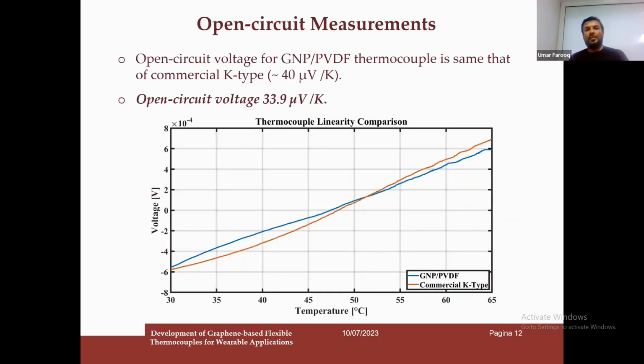So here are the open circuit measurements. They show us that the PVDF and GNP based thermocouple is following the same trend and the same linearity as the commercially available thermocouple. The commercial K-type thermocouple has an output of 40 microvolt per Kelvin, and ours was 33.9 microvolt per Kelvin, and they are following the exact trend.